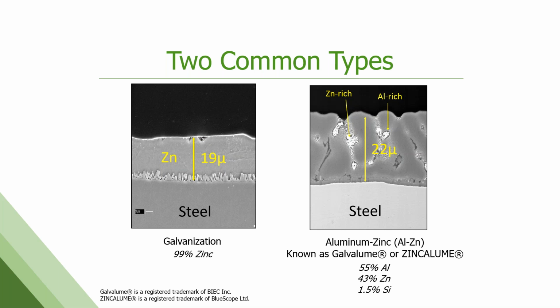This is an atomic level picture of those two products on a cross section. On the left is galvanized. So you can see it's 100% zinc. It's all very solid gray. These little crystalline structures are the interface between the iron, the base steel, and that coating that helps it attach, bonds together. On the right here is the aluminum zinc. So this gray area here is the aluminum. The white areas, I always think it looks like brain matter. The white areas are zinc areas. So you can see by volume, it's a lot more aluminum than zinc, which is why it has superior corrosion protection, because of all of that aluminum that's in there.